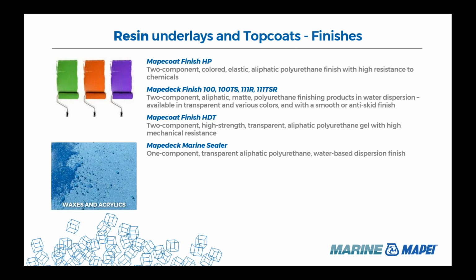And then the MAPEdec Finish HP is actually a colored resin coating that we can use to add effects or colors over a polyurethane screed or over a polyurethane coating as accents. The MAPEdec Finish 100 and MAPEdec Finish 111R are colored coatings that are water-based and designed to go over the top of a surface of either epo screed or the light screed, to go over the MAPEdec design. The 100TS and the 111TSR are clear coatings, also designed more like a sealer and a finish.